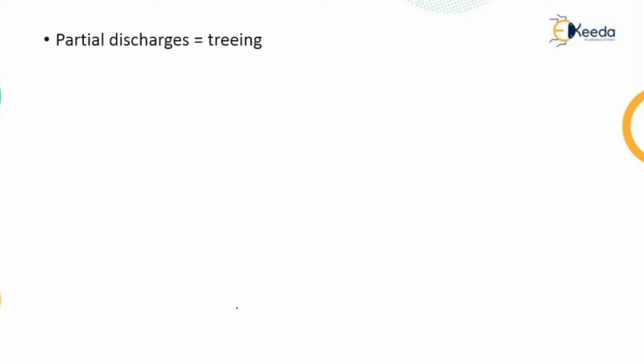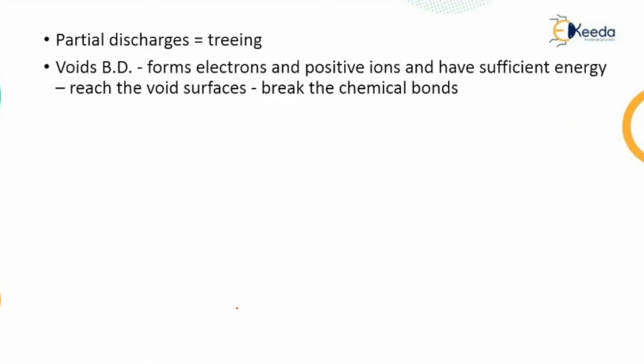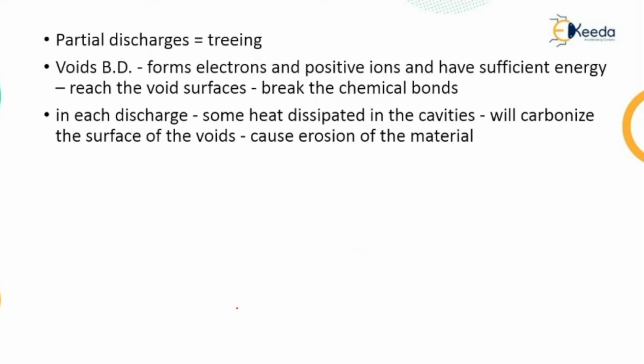When the breakdown occurs in the voids, electrons and positive ions are formed, and they have sufficient energy that when they reach the void surface they may break the chemical bonds. Also, in each discharge there will be some heat dissipation. Definitely when there is a partial discharge, the heat dissipation takes place in the cavities. So heat dissipates, which means there is a formation of certain gases, or maybe the carbonization of the surface of the voids. Whenever there is a formation of heat, the surface of the void gets carbonized and will cause the erosion of the material.